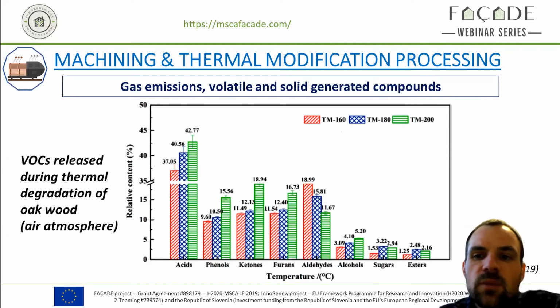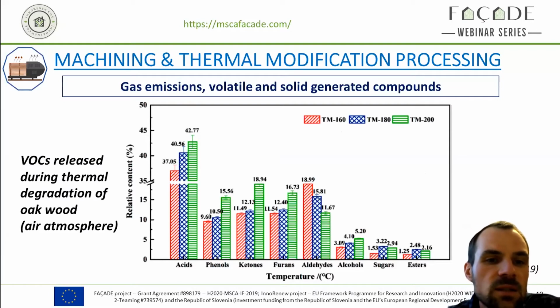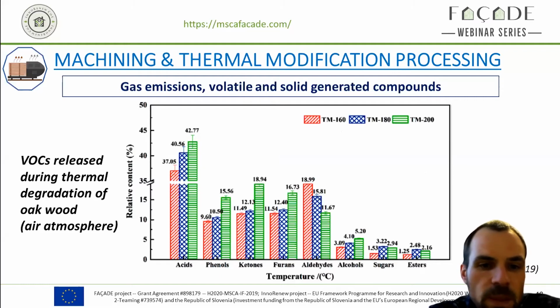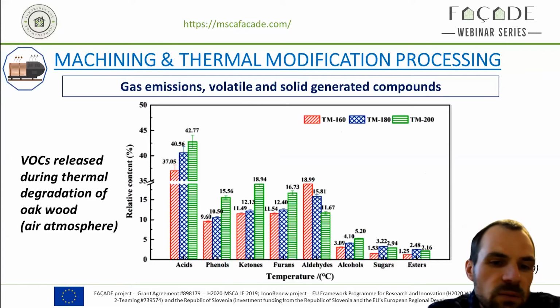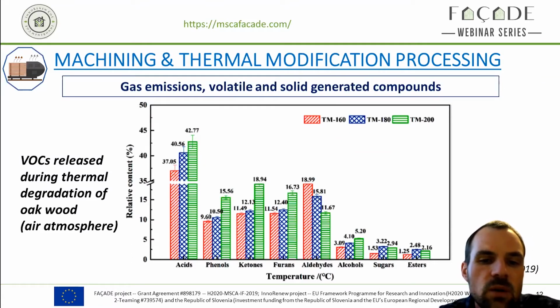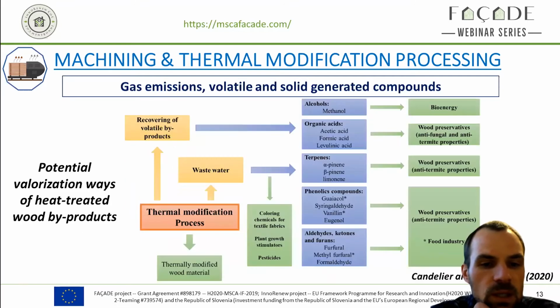And now another aspect of the thermal modification process concerns the emission of gas, volatile and solid compounds generated during the thermal degradation of wood. On this picture, we can see the different chemical compound families generated by the wood during its thermal degradation. The main volatile products are acids, phenols, ketones, furfural, and aldehydes, and we can also observe the generation of alcohols, sugars, and esters. For each chemical compound, it appears that the volatilization level increases with the heat treatment intensity, except for aldehyde compounds, which is mainly due to the lignin polymer reticulation.